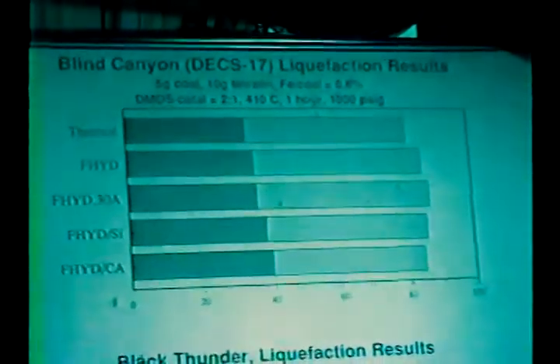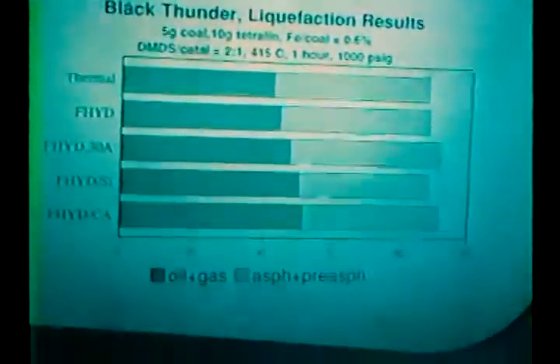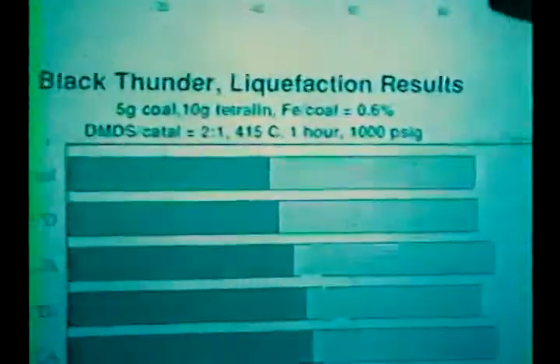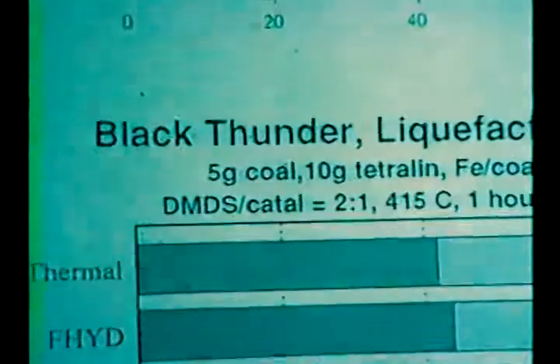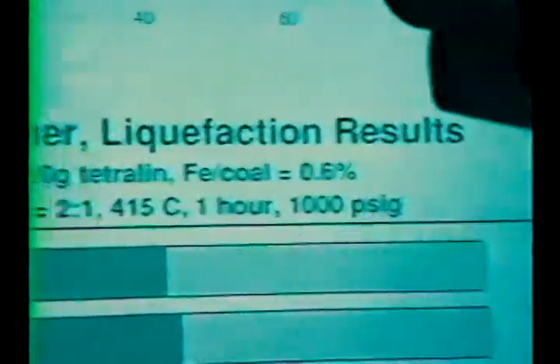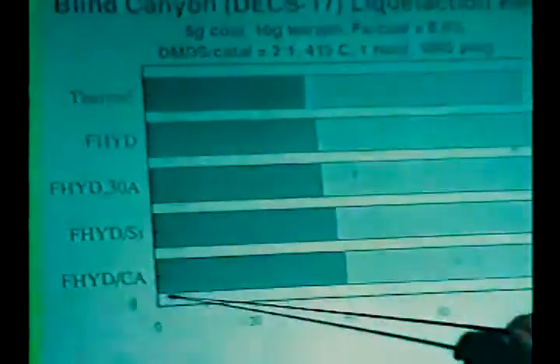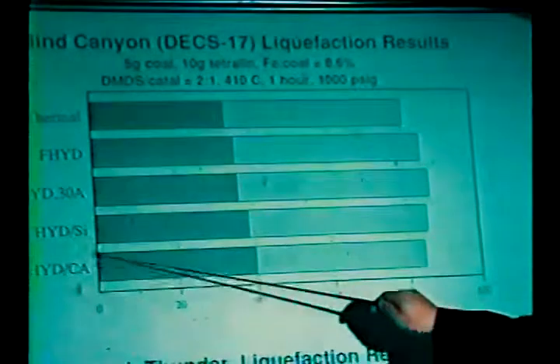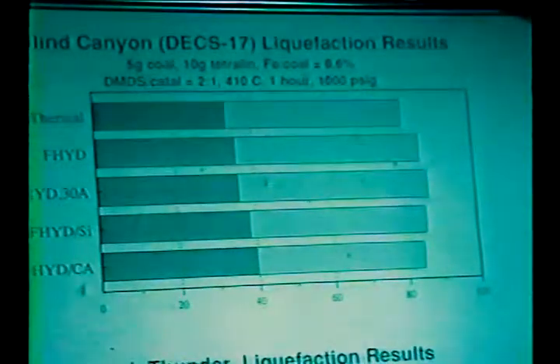Basically it's analyzed by extraction method, and the result is separated into two parts: one is oil and gas, and another part is asphaltene and preasphaltene. We test this as a thermal reaction. This is ferrihydrite without secondary impurity ions, this is the 30 angstrom commercial one, this is with silica, and this is with citric acid treated catalyst.